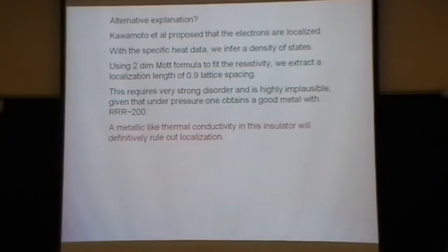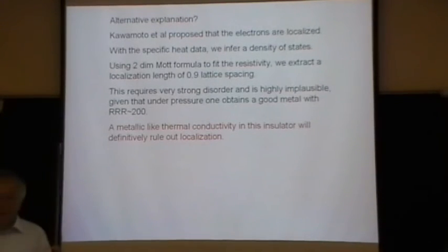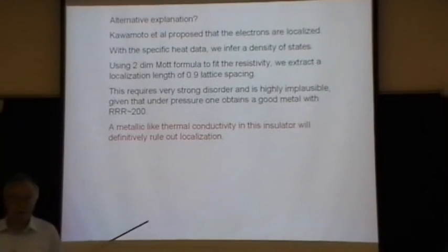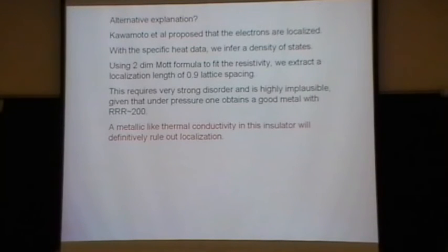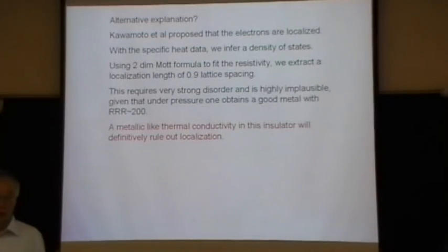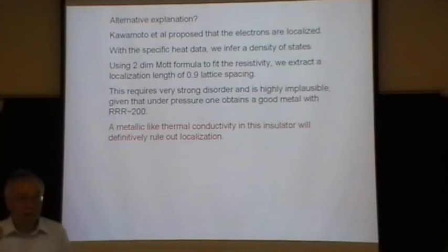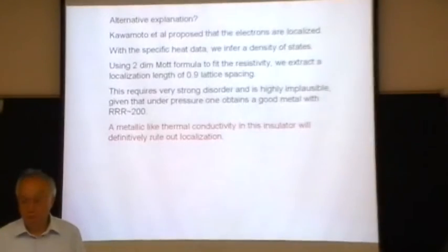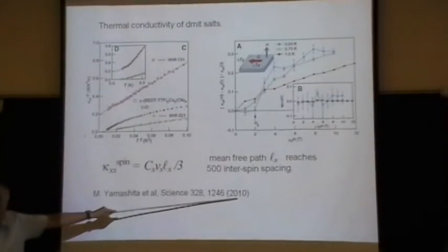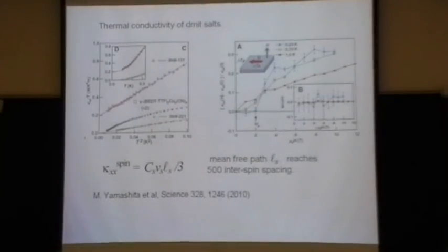If these are spinons, they carry spin. But transport of spin is very hard to measure. Spin transport is not an easy experiment. But these objects should carry entropy. Just like each one has spin degrees of freedom, they carry log 2 entropy, and so they could transport heat, just like a conventional metal. So these are real spinons, they should conduct heat like a conventional metal. And indeed they do. This is a very recent experiment, it just came out, I think, 2 weeks ago in Science.